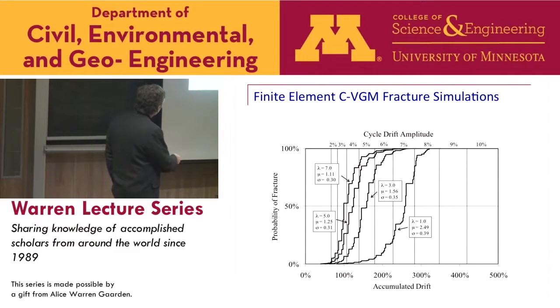this is the accumulated drift in the specimen. These black lines would be the fracture capacity, if you will, that's being developed in the different materials based on what we saw in the different heat affected zones we made and some of the base metal that was tougher out here. And of course, there's variability in that. And then when we take our maximum likelihood, this probability gives us our maximum likelihood estimate. So the estimate would be that this location would control as being the most critical.